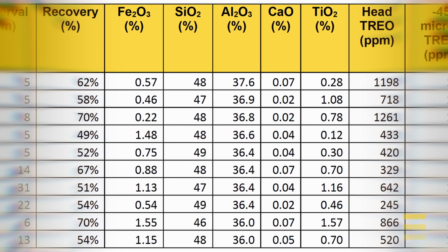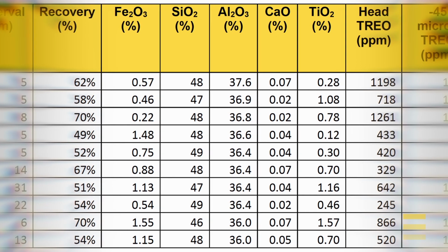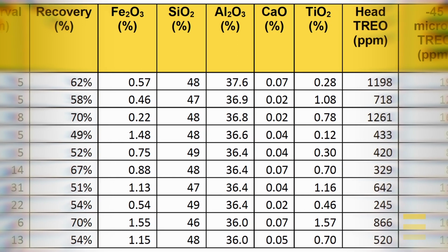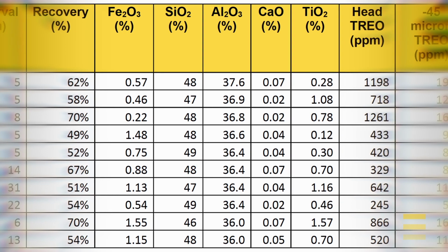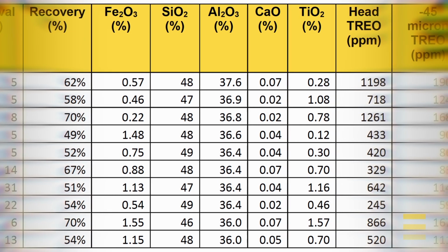What is also important is that the calcium is low. Now, the reason that it's important that the calcium is low is that calcium consumes acid, or it neutralises it. So when you're leaching out the rare earths in one of the processing steps, if you've got lots of calcium, or limestone is another word for it, that will neutralise the acid and won't allow you to leach out the rare earths. So the fact that our calcium is so low means that we hope to have very low acid consumption in that leaching step.